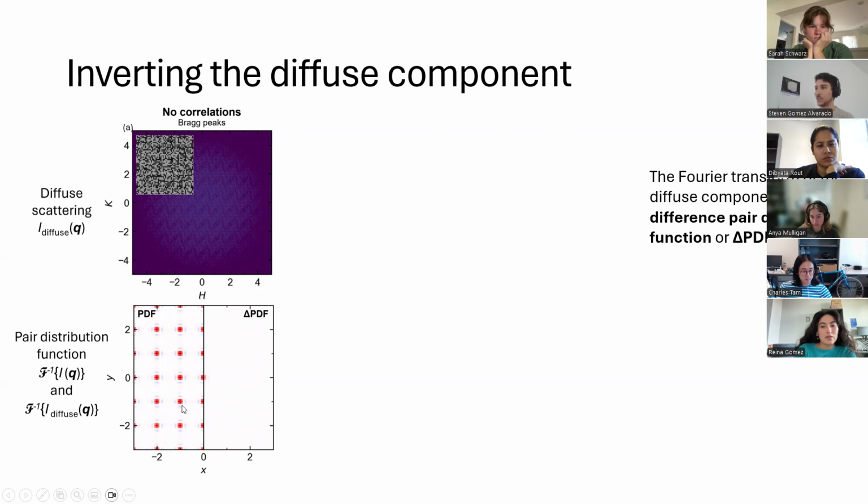So the average structure looks something like this. There's an atom on every site. Whoop-de-doo. Big surprise. But the DeltaPDF doesn't show anything because there's no correlations, right? So the average structure is the same as the local structure. Even though there's two atoms, black and gray, there's no enhanced probability of finding one or the other on every site.